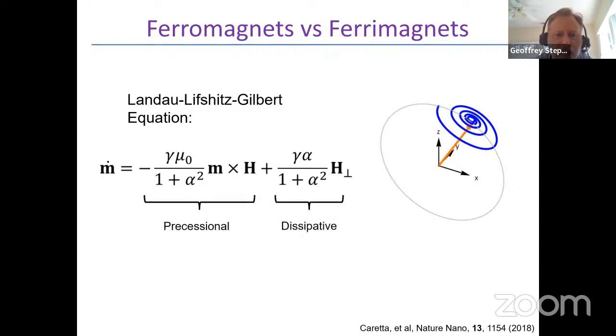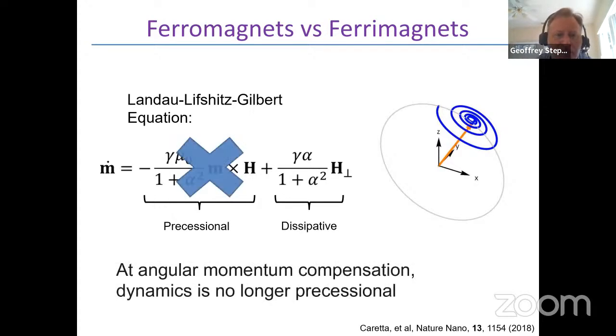But in a material with multiple sublattices that is at or very near compensation, the precessional term will tend to vanish in a modified LLG equation. And so the dynamics then are direct. If you drive a skyrmion, it will move in the direction that you push it, not at an angle to that. Or a magnetic domain wall will no longer experience precessional dynamics that leads to Walker breakdown.